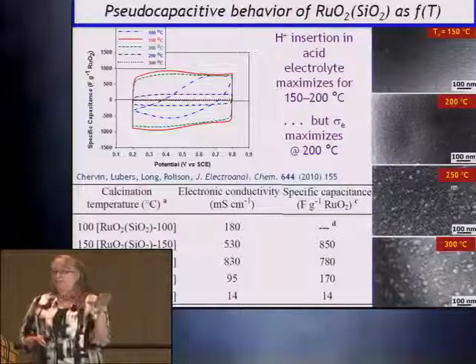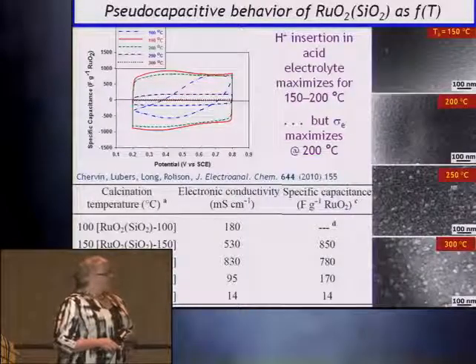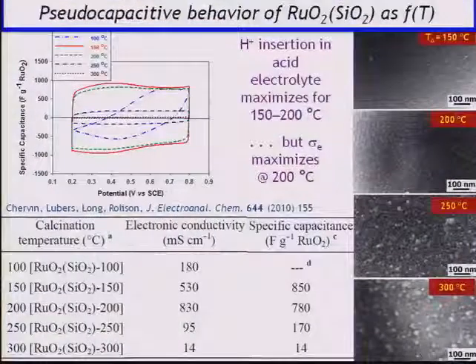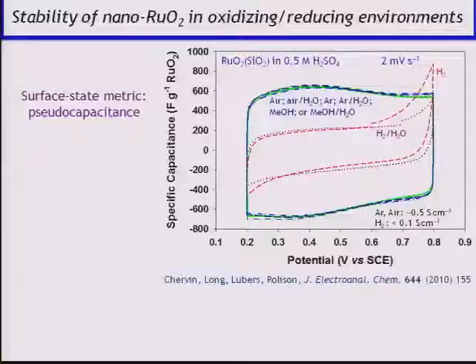So this system does what it kind of does in bulk, in the sense that you don't want to be too crystalline to store the maximum amount of charge, and you don't want to be too low conductivity to store the maximum amount of charge. There is a sweet spot that for this size of particle is sitting at around 150 degrees calcination in air.